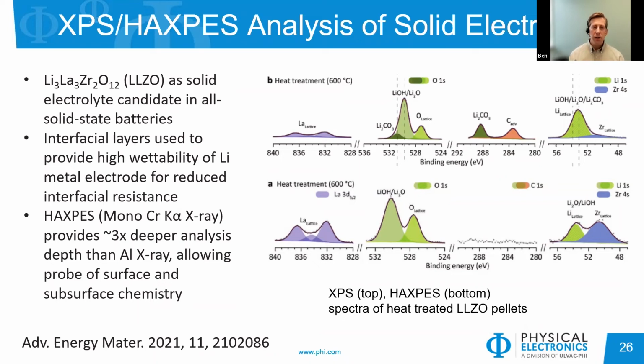LLZO is a candidate for solid electrolytes. One of the challenges with the solid electrolyte and the solid anodes is that interface, and making sure there is good contact and stable interfaces there. And so they're looking at a variety of different materials to provide wetting that can provide better wettability between the two.